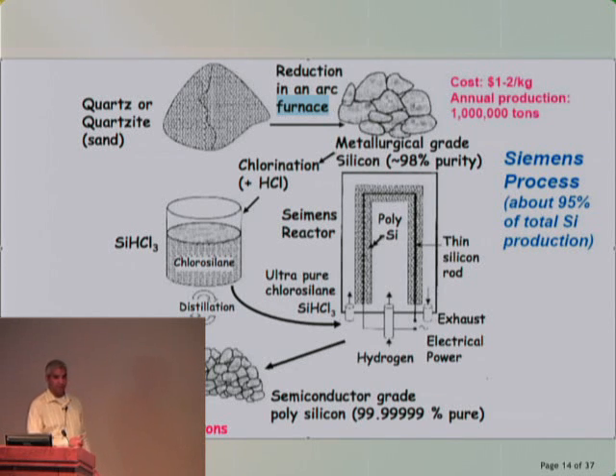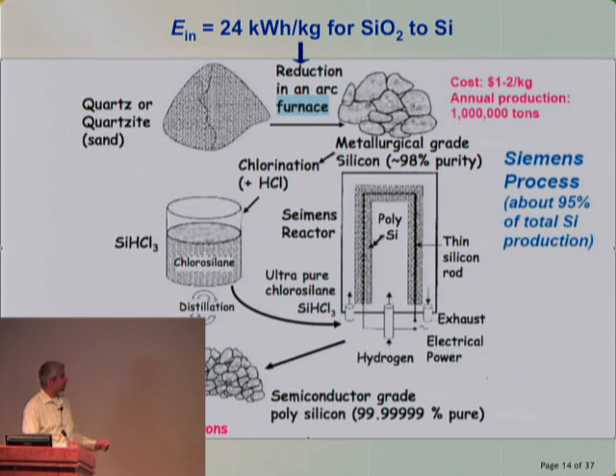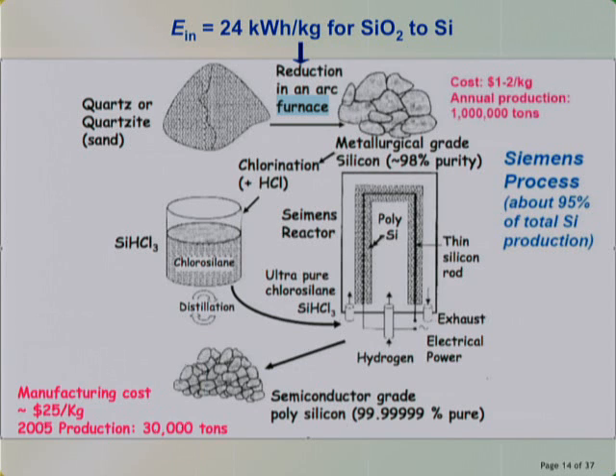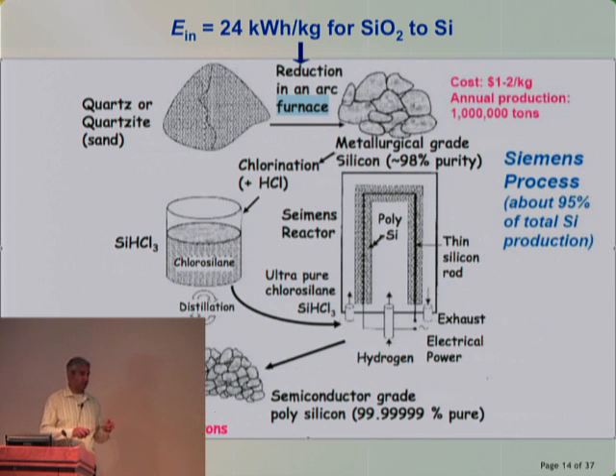We use an arc furnace to reduce that, and it has a fairly high energy input, 24 kilowatt hours per kilogram. Just to give you an order of magnitude comparison, if you were to do the same separation with an iron oxide, trying to separate the iron from the oxygen in a standard iron oxide compound, that number would be more like 2 kilowatt hours per kilogram. So out of the gate, silicon is actually quite high.